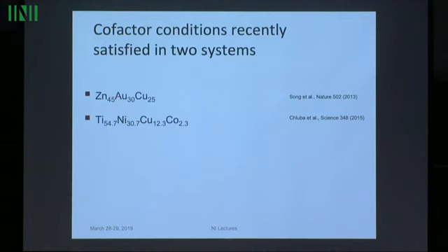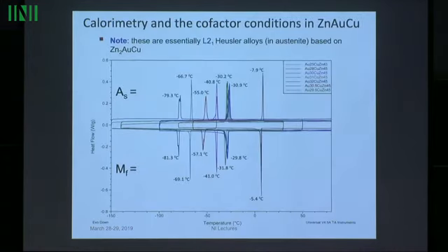This one was found in my lab when we did, like I said we did with the lambda 2 equals 1, we found a good starting point, and we just systematically changed the composition till we satisfied both these conditions, lambda 2 is 1, and this cofactor condition that I mentioned. It's, by the way, Sherry Chen's thesis, who's an organizer of this program, or the whole spring program.